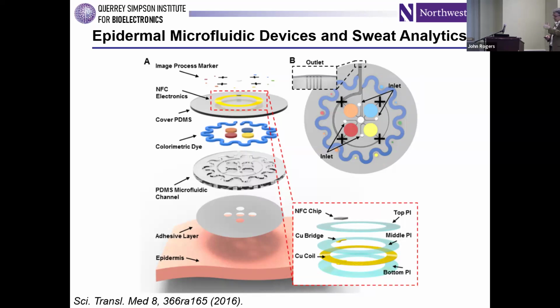We do the same thing with microfluidic lab on a chip technologies, traditionally made out of glass materials on rigid substrates. Could we make those skin-like? And it turns out you can, pretty straightforward to do that. So you can build soft microfluidic devices, very thin, very low modulus materials, elastomers. You can mold channels and valves and reservoirs. You can adhere them to the surface of the skin.